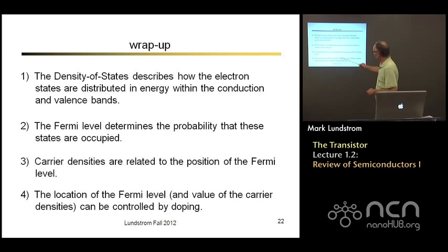The fact that we can mathematically relate the carrier densities to the location of that Fermi level. And the fact that what makes semiconductors so useful is that we can control by doping the location of the Fermi level and move it from anywhere down near the valence band to up near the conduction band edge.